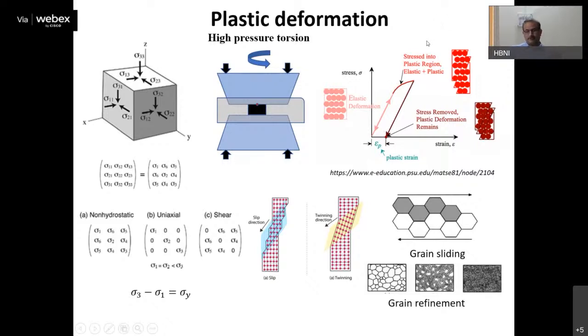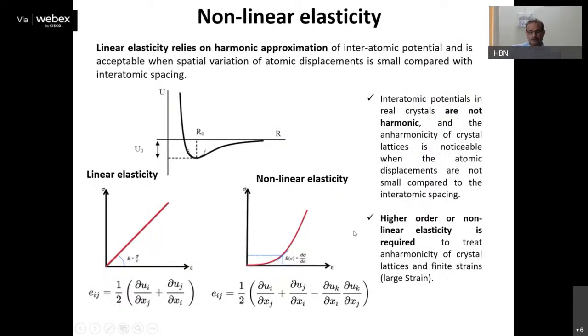So if the linear elasticity is a good approximation, what you should see is that whatever pressure you increase, the lattice strain, or the volumetric strain, should increase the same way. So it should follow a straight line. On the contrary, in experiments, what we see is that when you increase the stress, the strain does not increase much. So it follows a non-linear behavior.